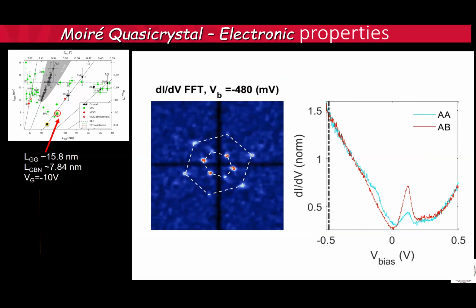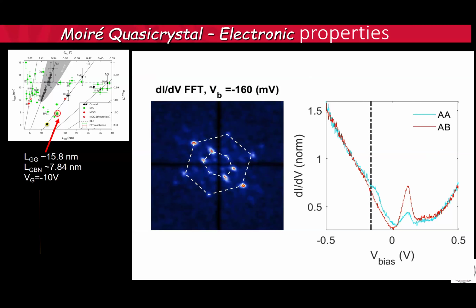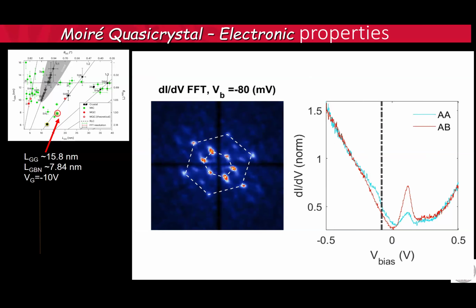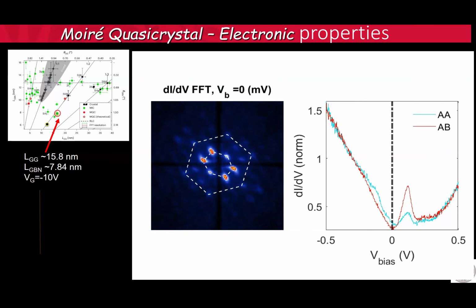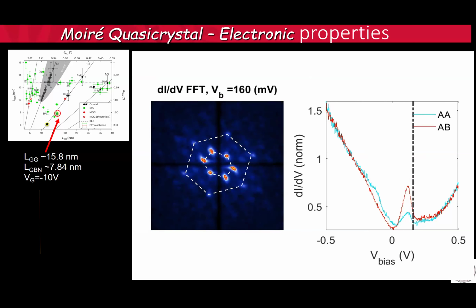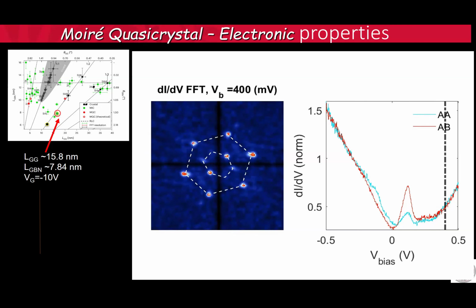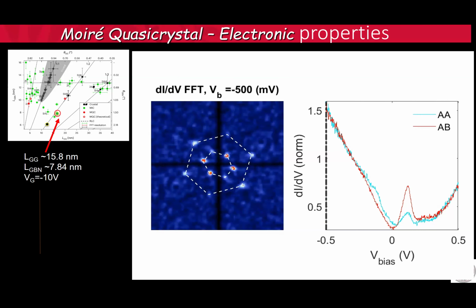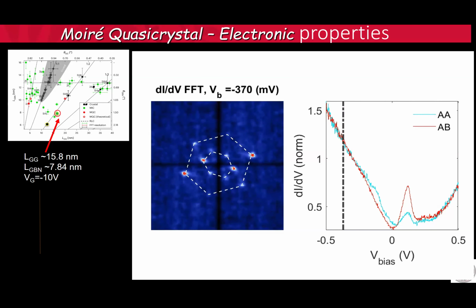So let me show you the movie now. So okay, I'm looking at this point here. And look, the outer ones are the KGBN and the inner ones are the KGG. And you see how some of them light up as a function of energy. And that has to do surely with you create localized states at different energy, and you get extinctions from the form factors going to zero for some particular energies. And that is because of the quasi-periodicity, where basically this is like a scattering problem, and there's some energy where you can go through and others you cannot.